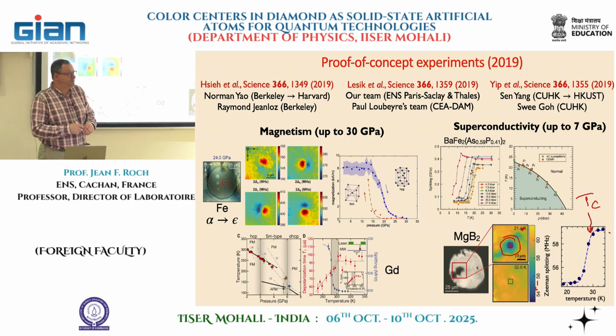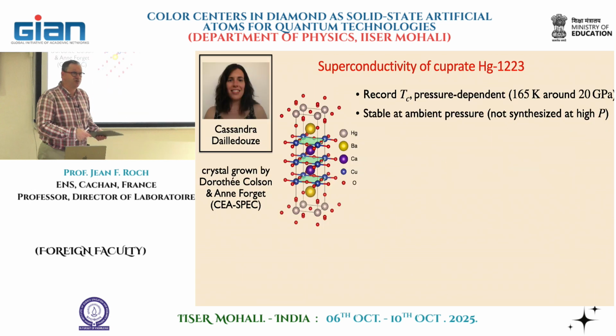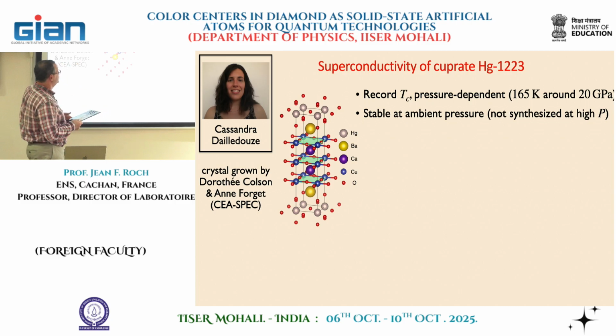Okay, so that's a kind of proof of principle, but now what we want is to go beyond that, to really analyze carefully what happens, and especially to detect the magnetic field penetration in the sample. For that, we studied, that was the work of Cassandra Dailledouze as a PhD student during the past 3 years, a very good sample that was grown at CEA by Dorothée Colson and Anne Forget. So what we have been doing is reproducing the experiment by Paul Chu in the 90s. And of course, the great advantage is that those systems are stable at ambient pressure. They do not require, like these superhydrides, to be synthesized at high pressure.